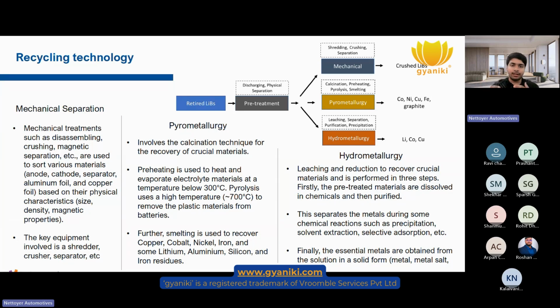So whenever you're shredding the complete battery pack, a particular type of shredder, which involves crushing, blowing, and many other operations, will separate the copper, nickel, aluminum, and plastic separately, and it will give you black mass separately. Now, this segregation is essential because the plastic, once segregated, will go into its own supply chain at 3 to 4 rupees per kg. Aluminum will go into its own supply chain at around 150 to 160 rupees per kg. And same with nickel. And then we have black mass.